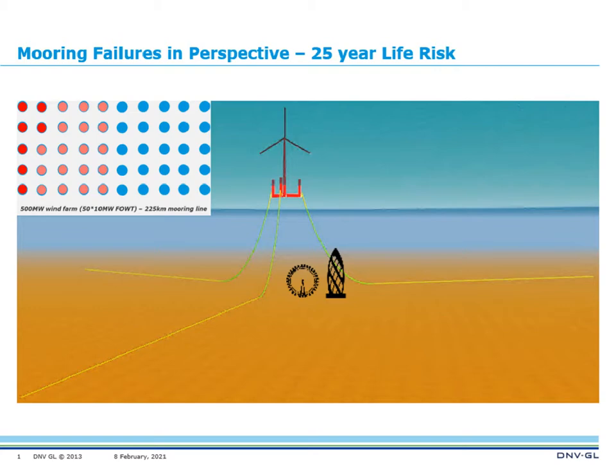So if we adjust the failure probability proportionally to the number of lines, this would translate to one in every 8 units experiencing a line failure in its lifetime, compared to the one in every 2 that I mentioned earlier. But let's take installation error, for example, as a common cause of mooring line failure. It might first appear sensible to expect that failure probability will reduce when having fewer lines per unit. However, when considering the wind farm as a whole, there are more lines to install. Also, there may be greater use of mooring rope components, which are particularly sensitive to installation, and I'll come back to this a bit later on.